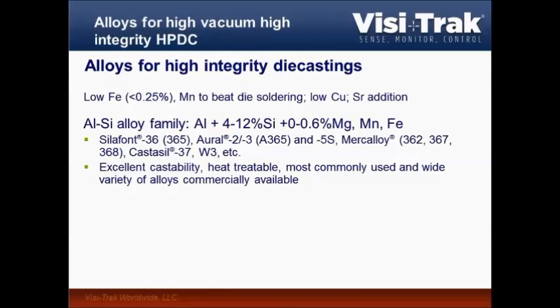If you look at wheels or suspension parts, typically you would use A356.2 as starting material. That means a primary alloy with 0.12 max iron, 0.15 typical in the part, while in die casting with a high freezing rate, as mentioned, we can go up to 0.25%.